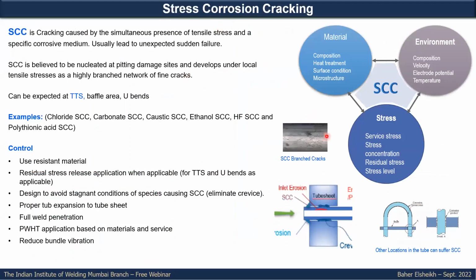For stress corrosion cracking, as we said, the material, environment, and stresses all should be present. It is one of the most common issues in this tube-to-tube sheet joint. In many cases, it is linked with crevice corrosion. If you have a crevice here, you might have an attack on the weld by stress corrosion cracking.